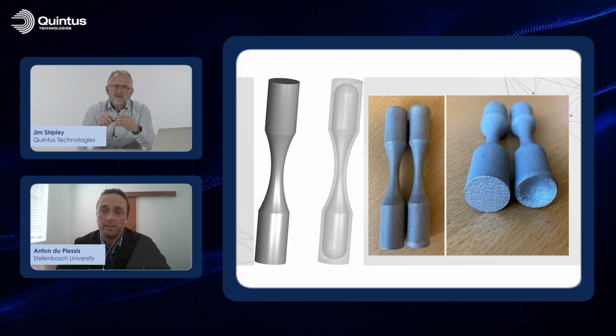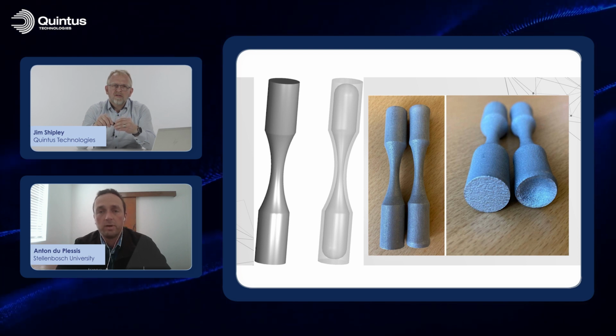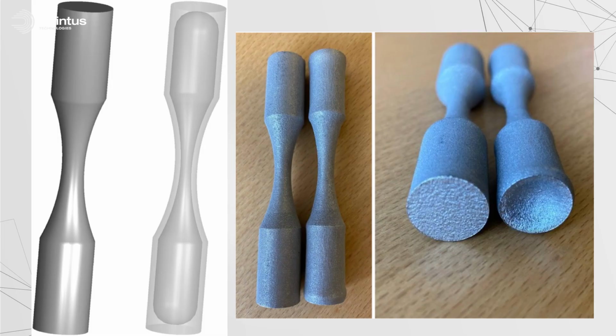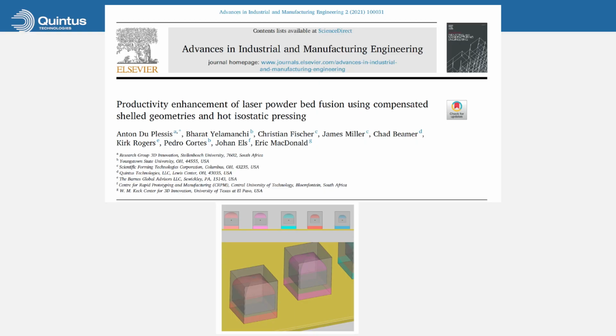Okay, cool. So the work you've done now, obviously speeding up the processing of the parts, maybe combining different powders, ensuring that you've got pore closure. What kind of mechanical properties have you seen for the titanium 6-4 example now? Well, surprisingly well. In the first paper that we wrote in 2019, I think, we compared rough, as-built surface condition solid laser powder bed fusion manufactured tensile bars and shelled bars, which were then HIPed subsequently to solidify them. And the tensile properties were identical. There's no difference. Both were quite good.